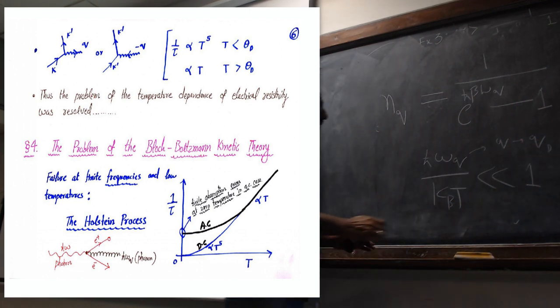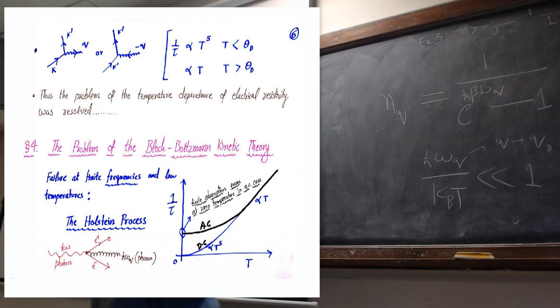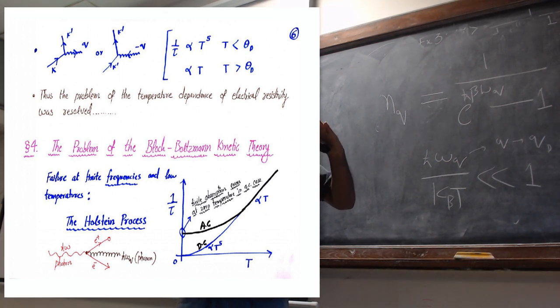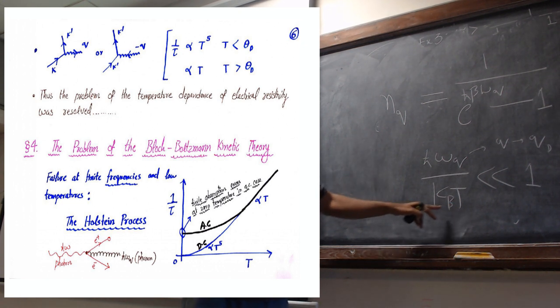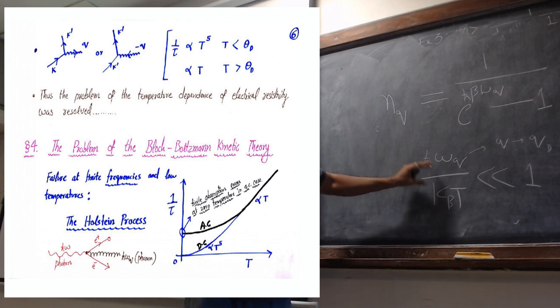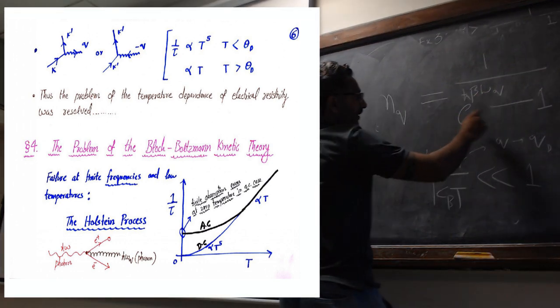I mean the maximum possible phonon energy, say 10 millielectron volt. Your kBT is much greater than that. That's the room temperature. Room temperature is 0.03 electron volt, 30 millielectron volt. Let's say the phonon energy is 10 millielectron volt. So this is very small. Then if this is small, you can Taylor expand it. So it will be e to the power.